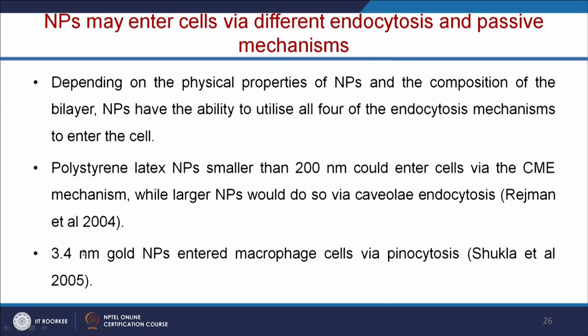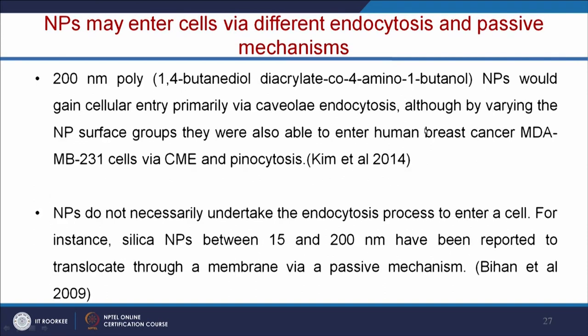And the gold nanoparticle with the diameter of 3.4 nanometer can enter the macrophage cells through the pinocytosis, and 200 nanometer polymeric nanoparticles would enter the cells through caveolae endocytosis. And by changing the nanoparticle surface groups, it can also enter the cancer cells by CME as well as pinocytosis process. So based on the surface charges, again the mechanism of cellular uptake will vary. So here the nanoparticles do not necessarily undertake the endocytosis process to enter the cell. For example, silica nanoparticles between 15 to 200 nanometer have been reported to translocate through a membrane through the passive